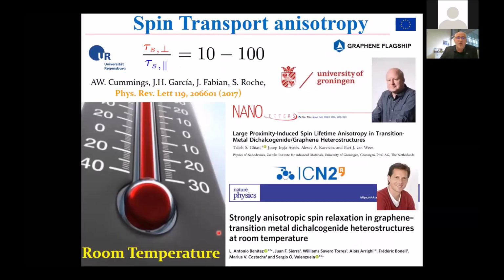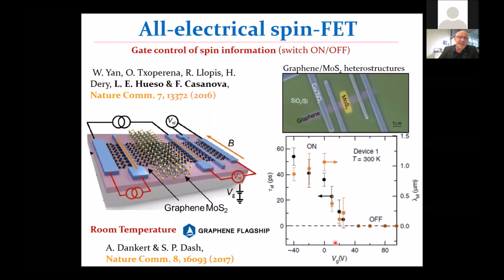At the same time, in parallel, our colleagues from the consortium, Bart van Wees at the University of Groningen and Sergio Valenzuela, studied different types of van der Waals structures with TMDs, and they confirmed that such a type of spin filtering effect could survive even to a very high temperature. In this work of Sergio, at room temperature, we get a factor of 10 or more difference in the spin lifetime. As I said before, there is also a possibility with a gate to tune the spin transmission in graphene, and at some point you could get absorbed into the bands of the TMDs where spin relaxes very fast. So somehow you can make an all-electrical spin field-effect transistor.